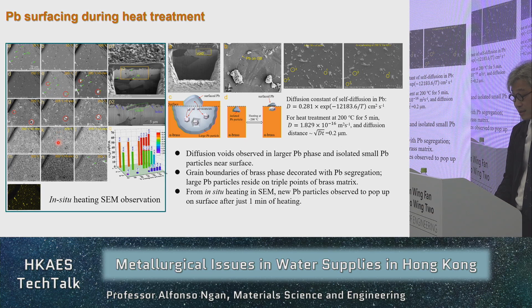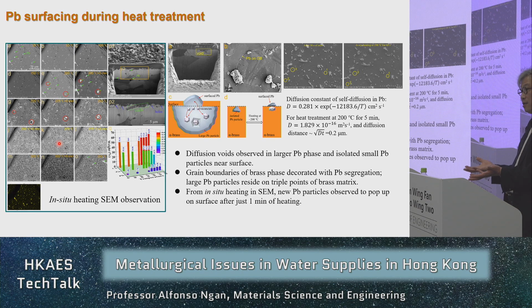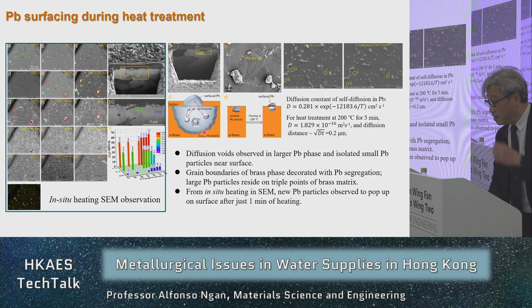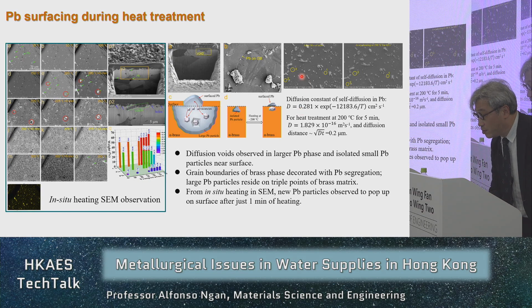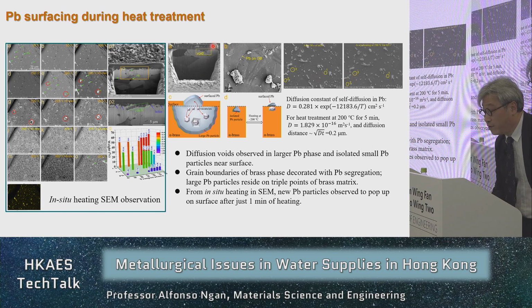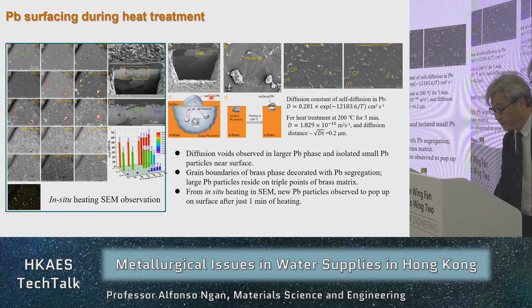But at the later stage, you also see holes inside. So the surface now becomes very dimpled. There are holes. Why? Because after the lead has diffused out, you form a void in the material. Some examples: if you compare this picture with that picture, if you look at circle 3 here, in circle 3 there is one more lead particle coming out. And if you look at the cross-section of the sample, you see these voids. They are called diffusion voids.